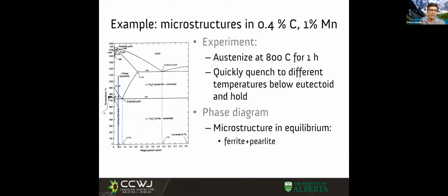And then we saw in the iron-carbon phase diagram these single phase regions where, for example, this marked as gamma says this is all iron with carbon in solution. We have this little triangle here that in reality continues down within the thickness of the line, and that is iron with almost no carbon in solution, and that is ferrite. That's a single phase. Cementite is like a line compound. This is a stoichiometric compound, and lives in this line.